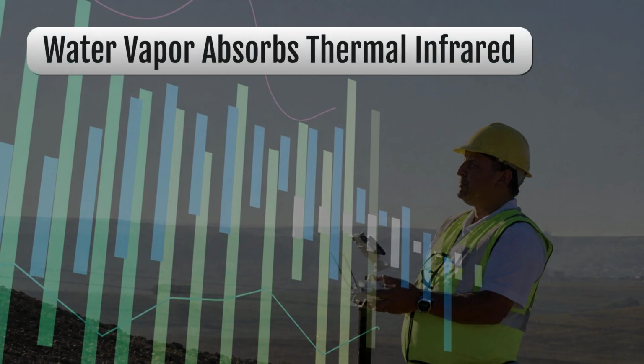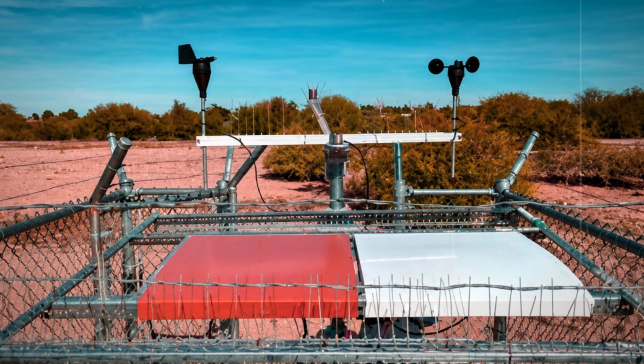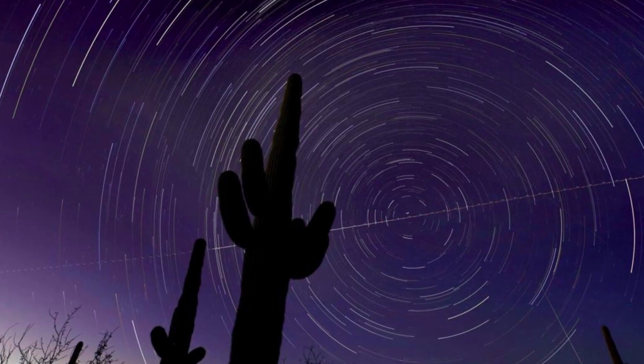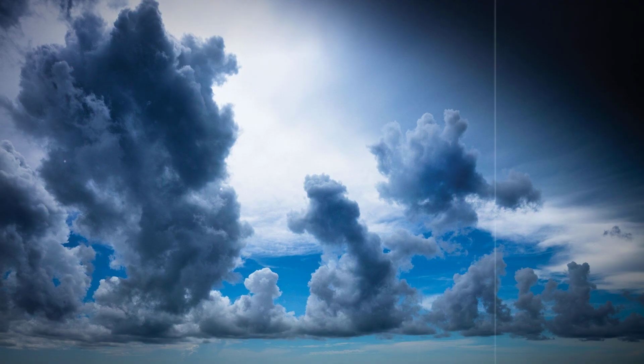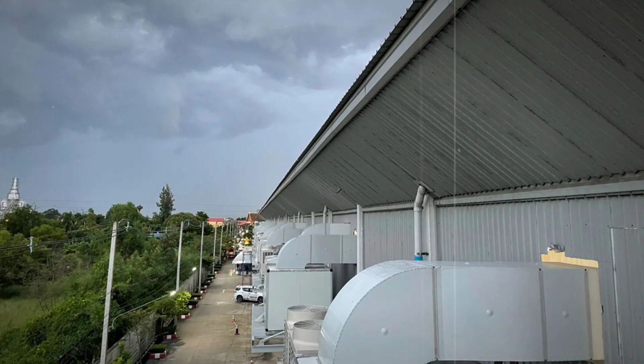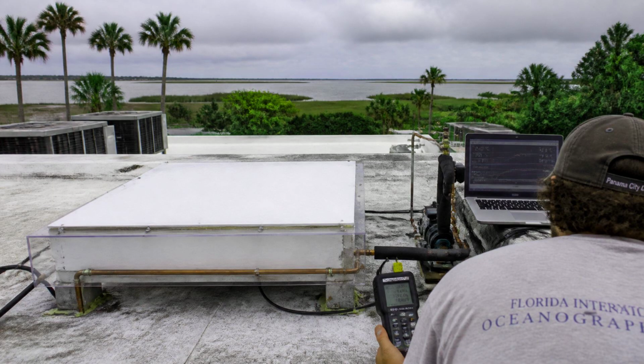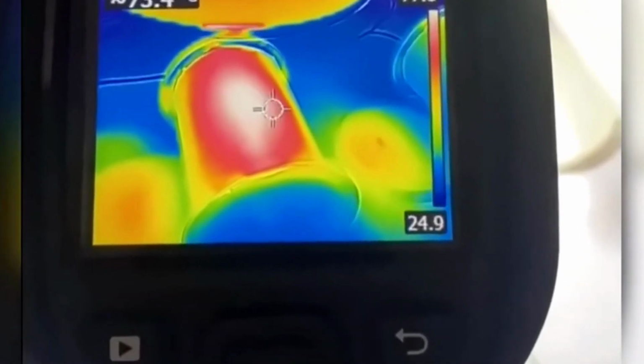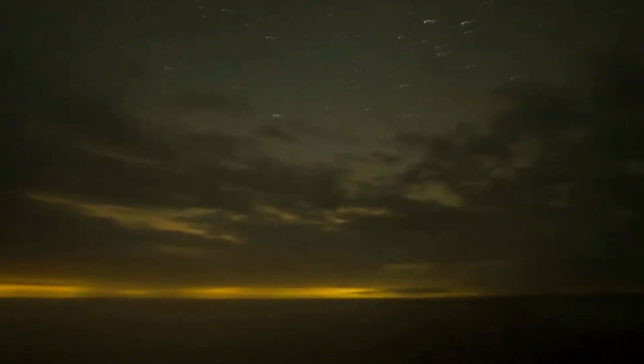The biggest is atmospheric humidity. Water vapor absorbs infrared radiation. In a dry desert climate, the atmospheric window is relatively open, allowing more heat to escape. In a humid climate, additional water vapor absorbs and re-emits more of that radiation. The sky appears warmer to the panel, reducing the amount of net heat it can reject. A panel that performs well in Arizona may produce much weaker results in coastal Florida or Louisiana. Nighttime performance may fall from several degrees below ambient in a dry climate to only 1 or 2 degrees below ambient during humid conditions. Clouds create another problem.